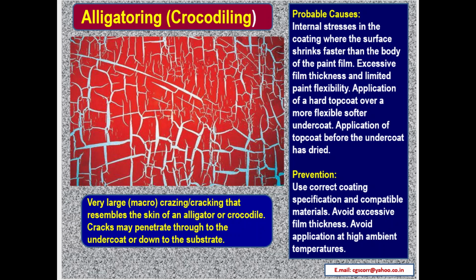The next failure defect is alligatoring, otherwise crocodiling. The figure on the left top side gives you a picturesque view of this defect. Very large macro crazing or cracking that resembles the skin of an alligator or crocodile. Cracks may penetrate through to the undercoat or down to the substrate. The probable causes are internal stresses in the coating, where the surface shrinks faster than the body of the paint film.